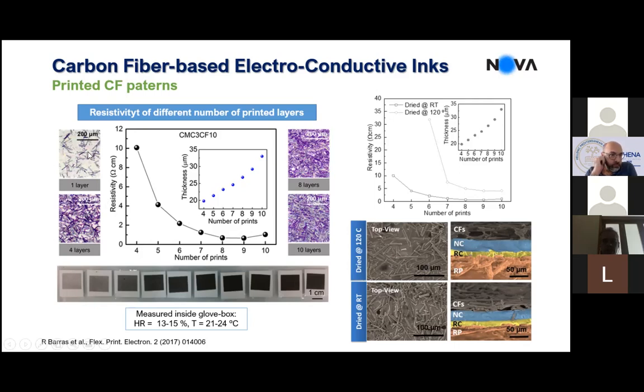So you see that with just one printing layer, you don't have a percolation path. Only above 4, you start to have this percolation path, and it stabilizes around 7. So you need to find the right printing procedure to find proper conductive properties for the printing patterns that you are making. And then also adjust not only the printing, but also the drying process. And here is just an example of how the resistivity of these layers compares if you dry it at room temperature, like you see here, and you dry at 120.